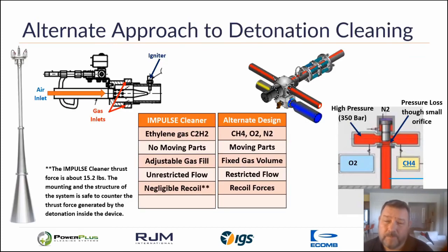There are a few approaches to pulse detonation cleaning. Our approach is to inject the gas and the air and mix it at the mixing head. There is no pressurization of the gases, and this allows us to create a series of rapid impulses, one after the other, very quickly. This is also advantageous in the cleaning effectiveness of those impulses. The alternate design would pre-compress gases in separate tanks and then combine them and ignite them under high pressure. This requires multiple gases and moving parts that eventually have to be maintained, and there is a restriction of flow as it has to make its way down the center tube to enter the boiler, and a loss of the overall pressure entering the boiler.